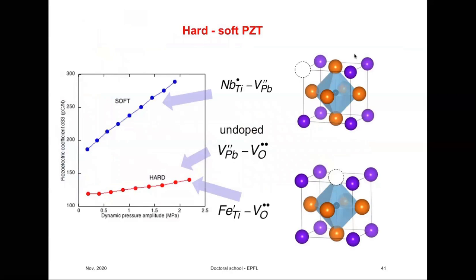characteristics. Let's compare these materials. So here is the piezoelectric coefficient as a function of dynamic pressure amplitude. This is a graph that I have shown you before. In a soft material, we have a large piezoelectric coefficient and a very large nonlinearity, while in a hard material, we have a much smaller nonlinearity and a much smaller piezoelectric coefficient to start with. And this immediately suggests to us that domain wall motion plays a role.